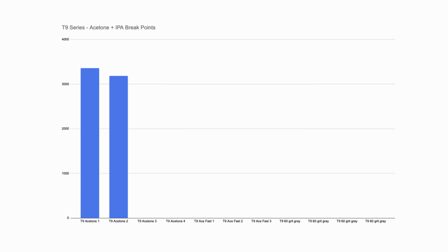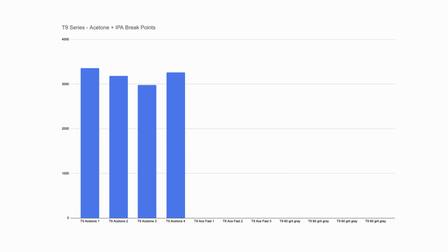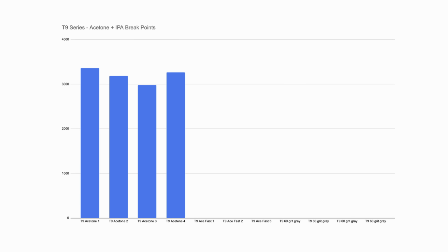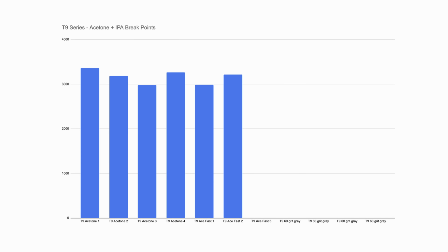Folks, the results are in. We're looking for consistency. Let's see if we got it. For the straight acetone and IPA wipe, we've got 3350, 3200, 3000, and 3260. Awesome, all in the same area. For the fast bonded acetone and IPA wipe, we have 3000, 3200, and 3250. Same ballpark, no huge difference in strength. So bonding immediately versus 15 minutes after mixing had no real effect.